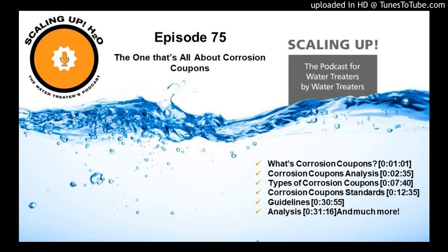And then once that's done, we take a final picture of what that coupon looks like front and back after it's cleaned. And then we start doing math. We do the equation to figure out how many mils per year was lost during that exposure time. And again, mils per year is 1,000ths of 1 inch. And then we go ahead and write our reports.